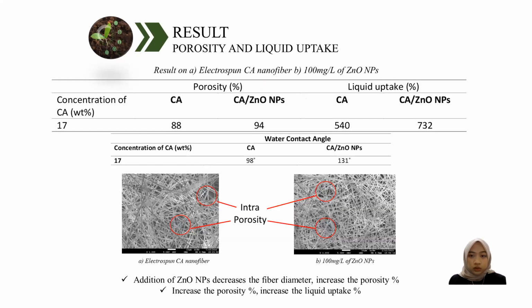And for the porosity and liquid uptake test, as we can see here, compared to the cellulose acetate, the cellulose acetate with the inclusion of zinc oxide nanoparticles nanofiber has higher porosity and liquid uptake. This might be due to the porosity of the nanofiber and also the diameter of the nanofiber. With the finer diameter of nanofiber, at a smaller scale size, the porosity is higher and the liquid uptake is higher. Thus, this is favorable for the seed coating element.